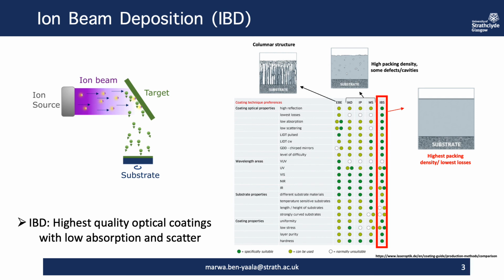For all the projects I mentioned, our work is based on ion beam deposition technique. So in this slide I will briefly present what is IBD and why we use it. So the ion beam deposition technique is the most advanced deposition technology for the most critical demands on optical coatings. So it works with a source, where gas molecules are ionized and accelerated onto a target. Then the coating material is sputtered off and deposited on a rotating substrate to form the thin film.